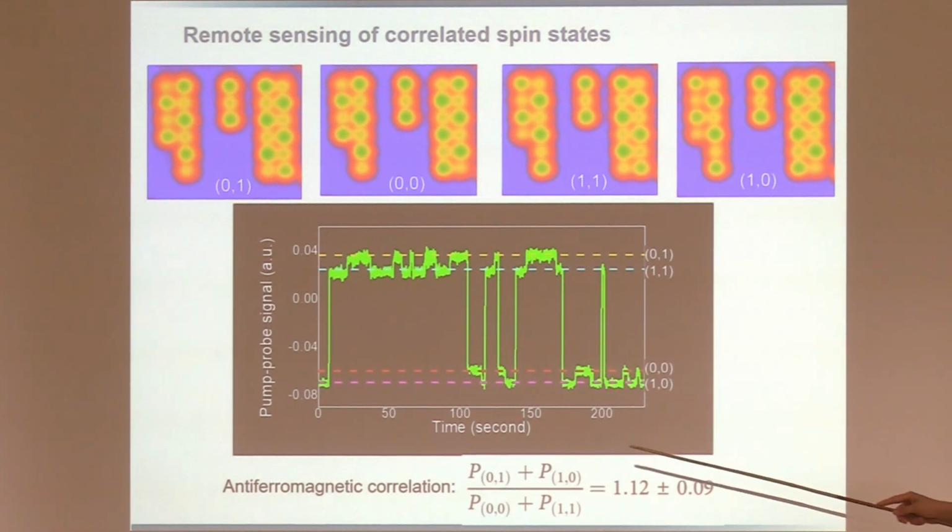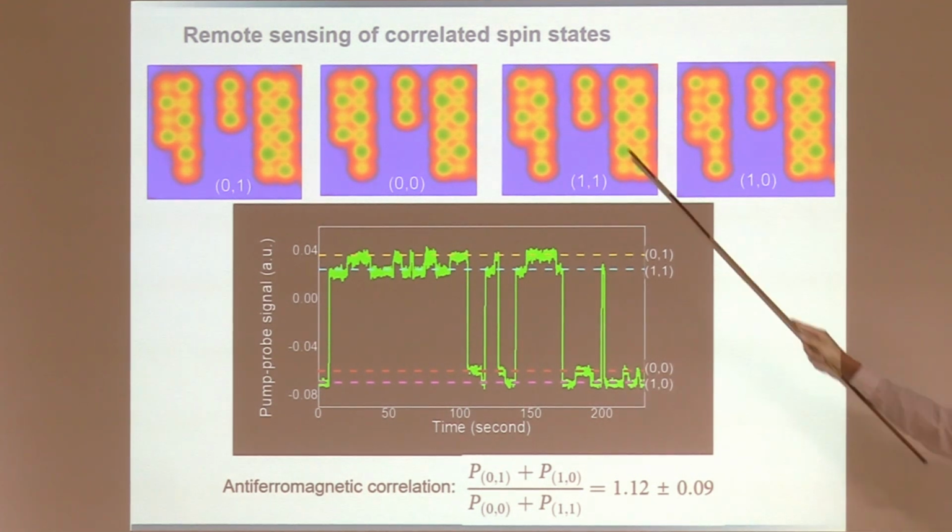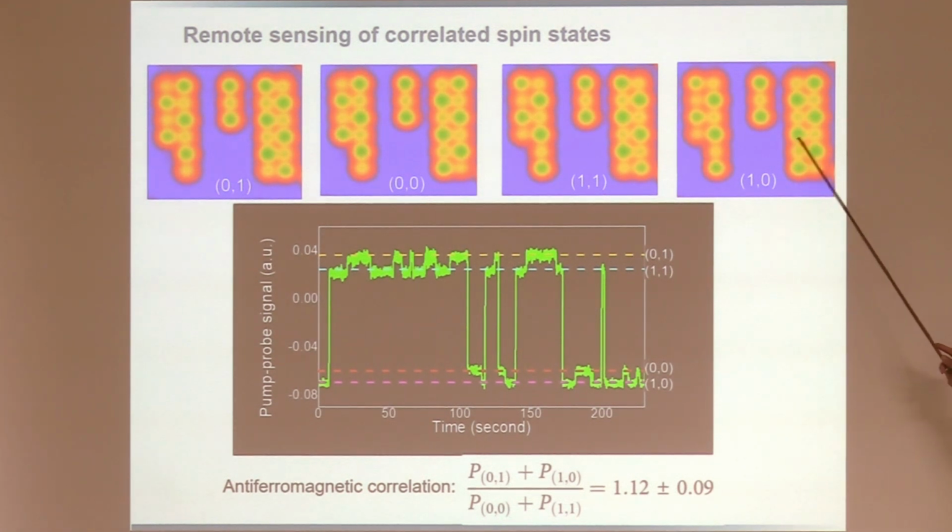To be fully open with you guys, when we did this measurement, we did not know this. We were under the impression our tip is a few nanometers away, we don't use too many tunneling electrons. After all, our bias voltage is only on for a few nanoseconds every few microseconds. So the duty cycle is very low. We were like, it'll be fine. Turns out it's not. You need to play a few additional tricks to really get into the regime to not perturb the switching. Which actually means that in the end, it took us quite a few years to ever see the intrinsic switching of such a structure. All right, at lunch, if you like, we can talk more about this.